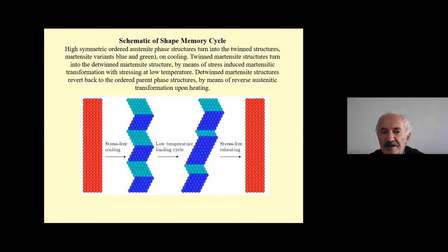This is the schematic of the shape memory cycle at the crystallographic level. Let me inform you that the shape memory effect and superelasticity are performed in the beta phase region of the material, and an ordered phase is essential. On cooling, ordered parent phase structures turn into twinned martensitic structures by means of thermal induced martensitic transformation. The second step is deformation, and with the deformation, twinned martensitic structures turn into detwinned martensitic structures by means of stress-induced martensitic transformation. On heating, detwinned martensitic structures turn into the ordered parent phase structures by means of reverse austenitic transformation.